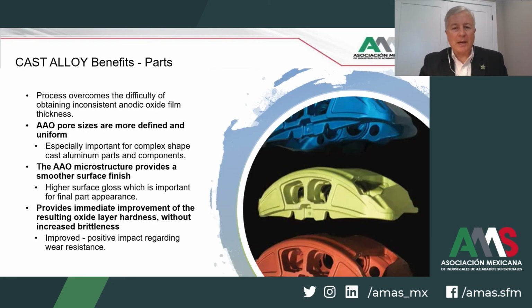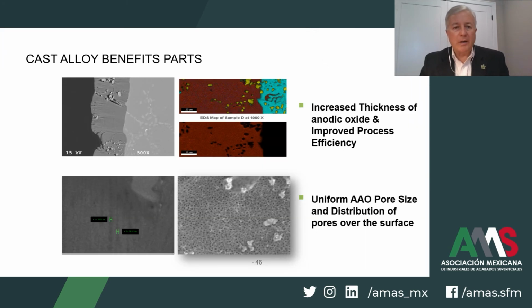Managing the casting manufacturing to minimize variables and provide a greater consistency with the casting surfaces and the casting condition will realize a lot of benefits. The benefits for parts originate from a thicker layer that is more consistent. The defined anodic structure, pore structure is improved, with the microstructure being more smoother. The anodic oxide layer surface finish offers a brighter surface. You have better color depth, and the hue of color is greater. And there's improved hardness in the oxide layer, which is going to be more resilient to wear interactions in its final application or use. There are quite a bit of benefits for the parts.